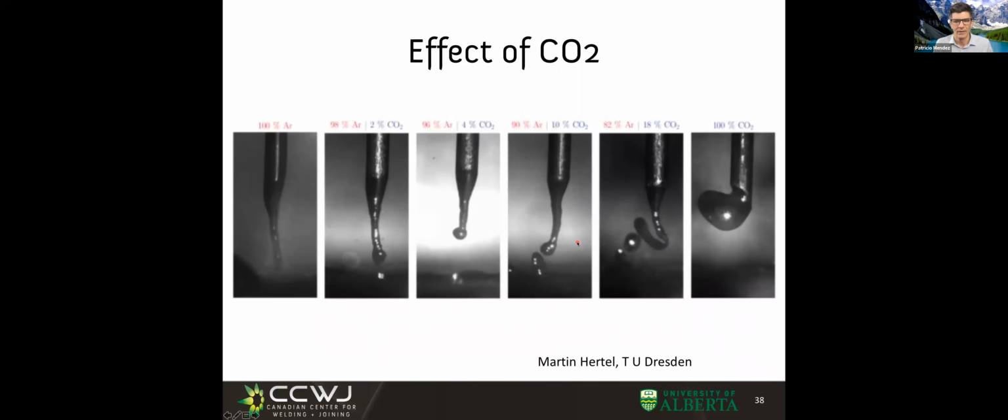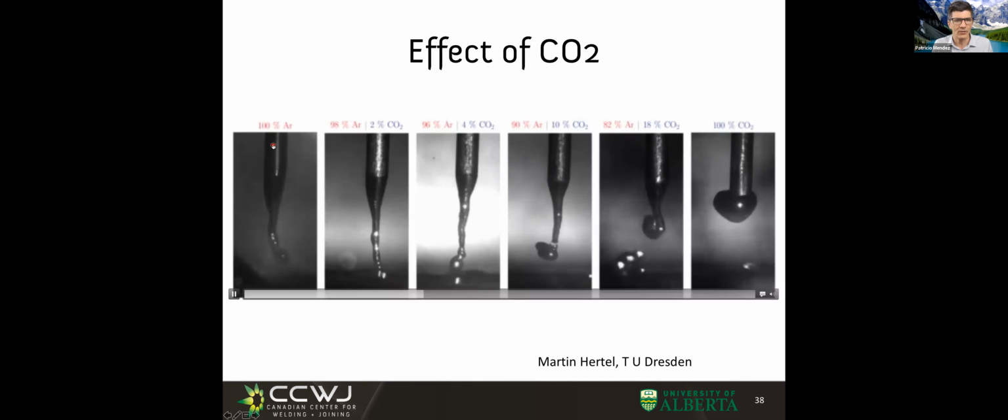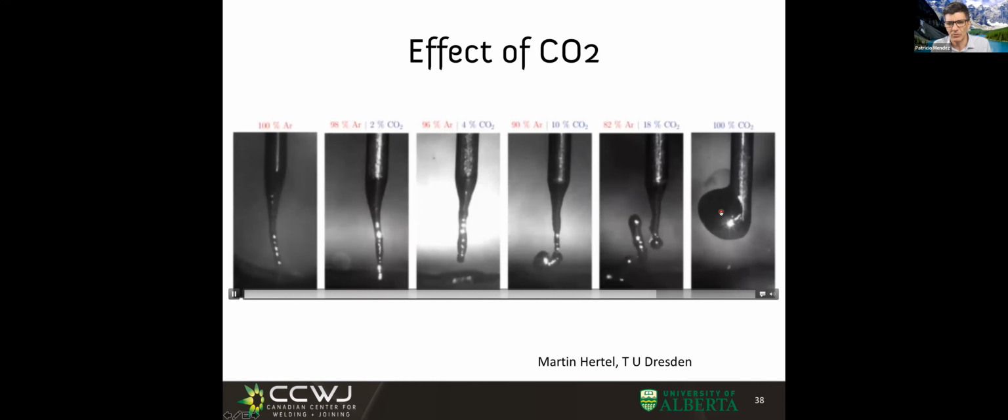But the cool thing is this is done by a super talented, now he's a professor in Germany, who did this very systematic set of videos from 100% argon to 100% CO2. I would have liked to see what happens after 18% CO2, but you get to see how you have a long tail with 100% argon, and how the tail gets shorter and shorter as we have more CO2.